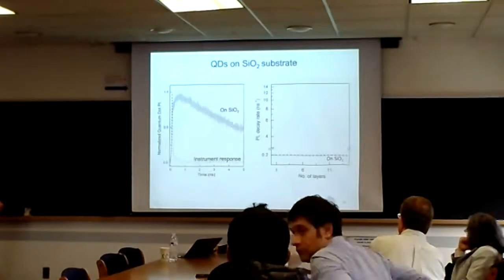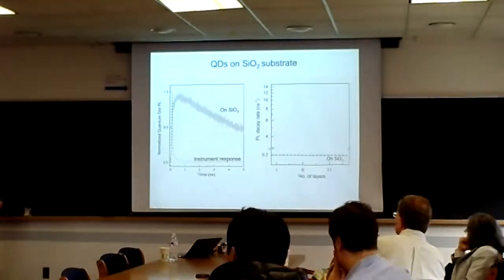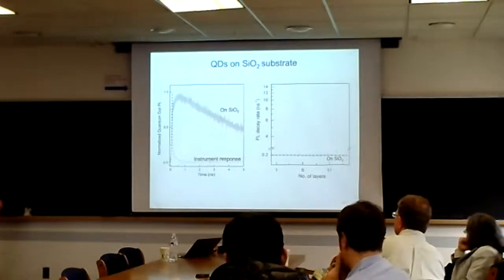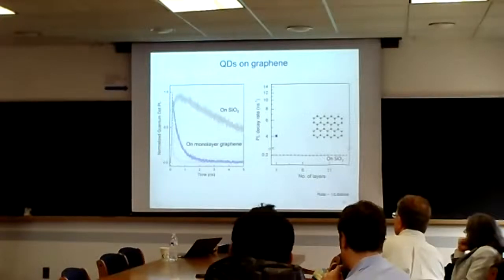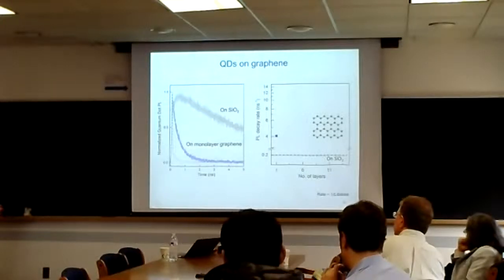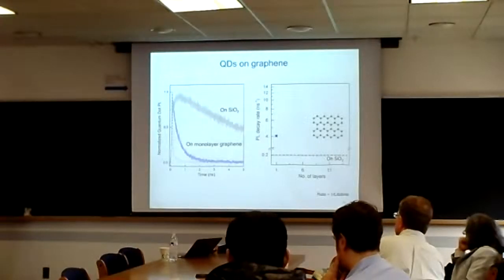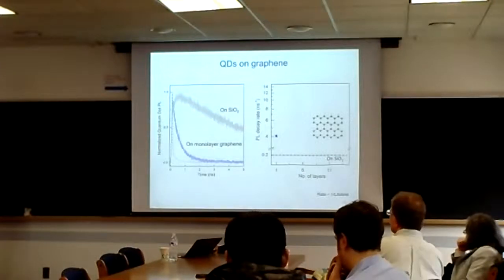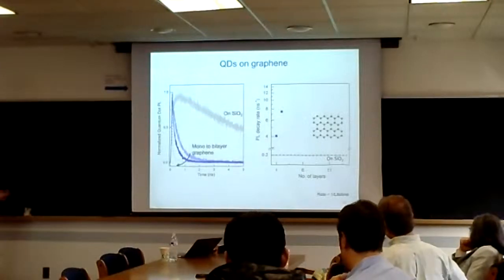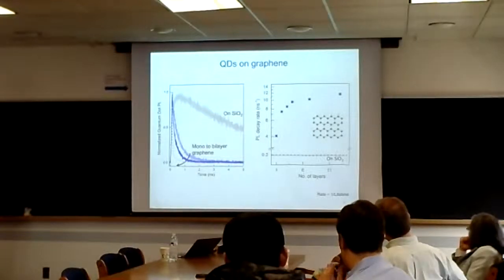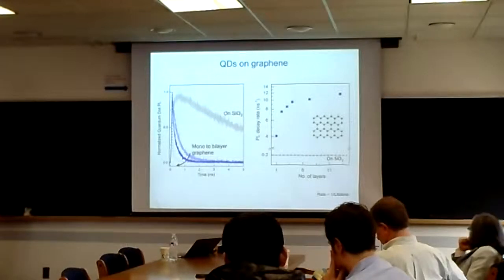In terms of the data, we have quantum dots on a substrate. This is the decay curve over many nanoseconds, and the instrument response is much sharper, so we're confident we can see these emissions very well. When we do the exact same experiment on top of a monolayer of graphene, the decay rate goes up by an order of magnitude. That matches the light emission going down by an order of magnitude in those wide field maps. We do this experiment again with an increasing number of layers of graphene, and this saturates very quickly to a value within a few layers.